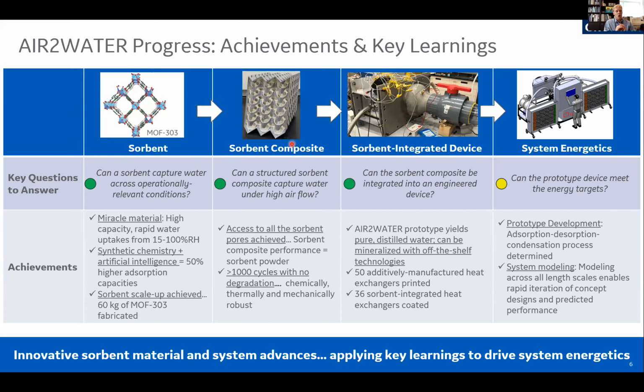We can get access to all of the sorbent, even with the use of a binder that integrates this into a general structure. So we see this equivalent performance. We've got more than 1,000 cycles with no chemical, thermal, or mechanical degradation. This is a very robust system when you start to integrate this into these devices.